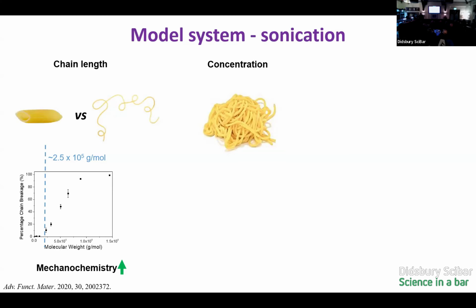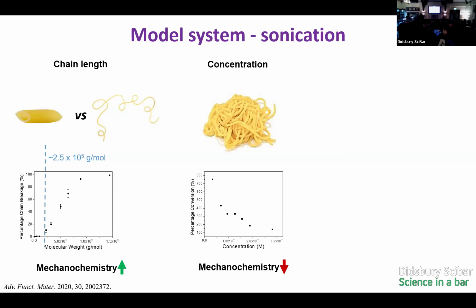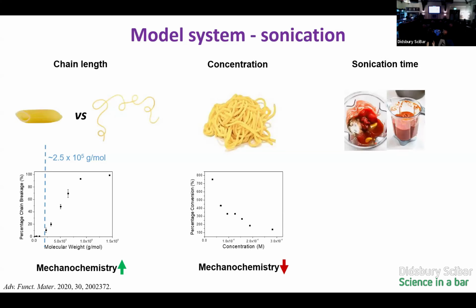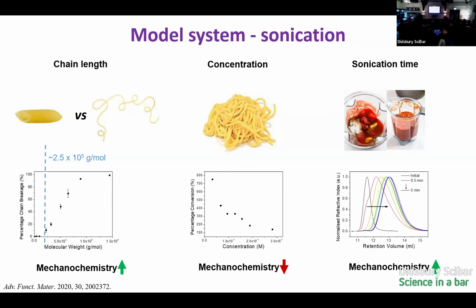Whereas if we just had a single chain, it would be kind of easier to pull it out and extend it and get enough tension in the chain. So we get a reduction in the amount of mechanochemistry we see. And then, as we'd expect, if we sonicate it for longer, essentially if it has to experience that really turbulent and violent system for longer, we get an increase in mechanochemistry. So we get more mechanochemistry as we increase the sonication time.